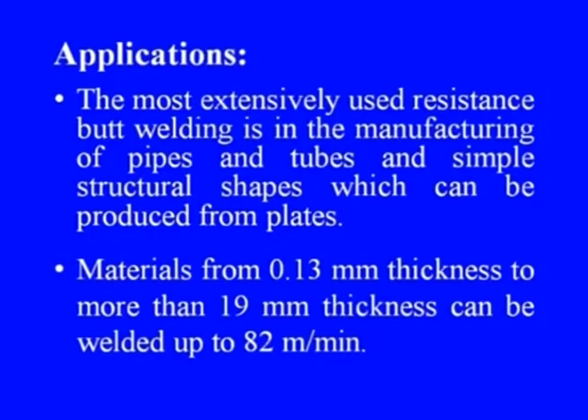Now, let us look into the applications of this process. The most extensively used resistance butt welding is in the manufacturing of pipes and tubes and simple structural shapes which can be produced from plates. Materials from 0.13 millimeter thickness to more than 19 millimeter thickness can be welded up to 82 meter per minute speed, which is quite high. Almost all types of materials can be welded by this process.